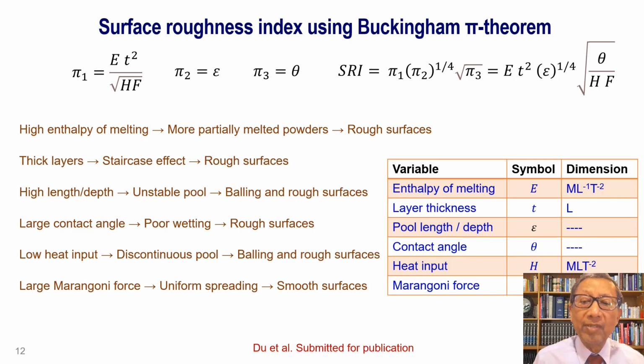We can use Buckingham Pi theorem to make a model for surface roughness. The important variables are listed here. High enthalpy of melting, whether or not it takes a lot of heat to melt the feedstock, is an important variable. If the layer thickness is high, then the surface is likely to be rough because of a staircase effect. High length to depth indicates an unstable pool, and therefore the surface could be rough because of that.